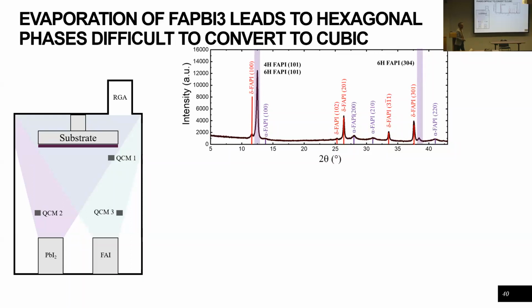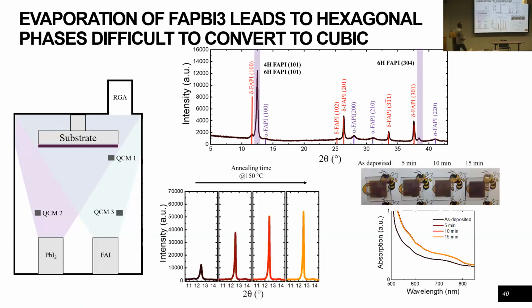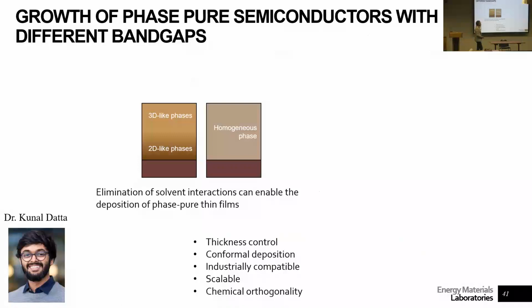So far, we've been having a lot of trouble growing perovskites. That purple shaded area there, and this one here, these are impurity phases that we don't want. What we want is this little guy here. That's the alpha phase of the perovskite, which actually is not forming. And there's nothing really that we've done that leads us to forming the actual perovskite. We've actually been forming these impurity phases from evaporation. And so a lot of what we're doing is trying to understand how to form those phase pure materials and what kind of things we can do to enable it.